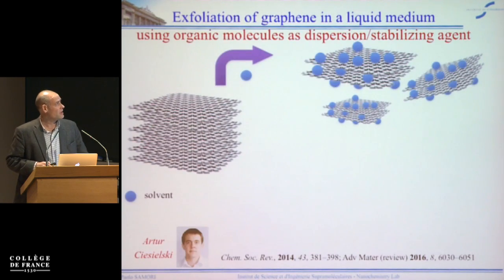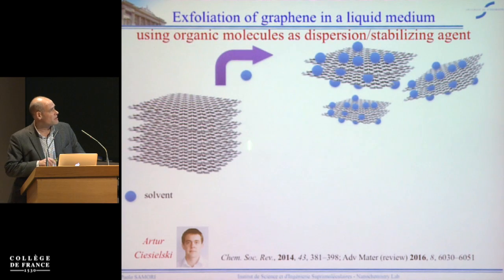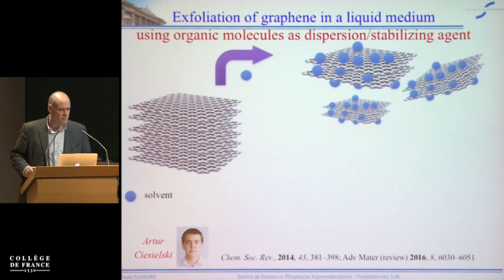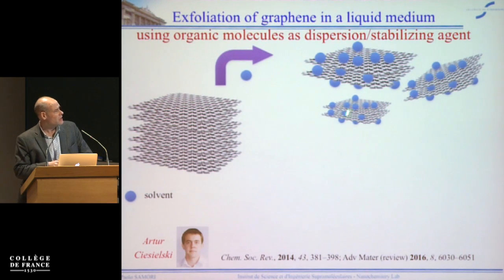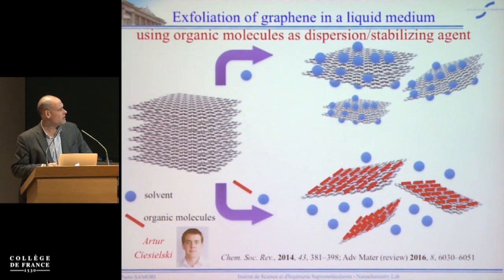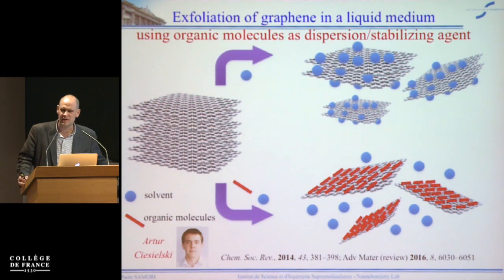Now the idea is very simple here. You start from graphite powder, you put this in a given solvent, and you do a cycle of sonication and centrifugation. Sonicate to exfoliate, and centrifugation in order to purify. Now, you have to choose the right solvent. Usually this is NMP. And eventually, it is said in the literature that you can use surfactants as stabilizing agents. Okay, so the surfactant can be this red bar. These are organic molecules. Now, the question as a chemist is what is the best organic molecule you can use?